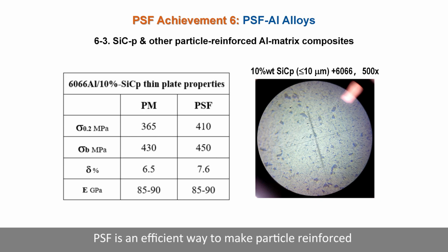PSF is an efficient way to make particle-reinforced metal matrix composites. The photo shows 10% silicon carbide particles of 10 micrometers uniformly distributed in alloy. It is of the same ease to make particle-reinforced steel or other alloys. At the same modulus of elasticity, PSF can achieve better tensile strength and yield strength than PM counterpart.